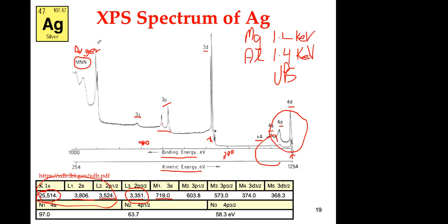The kinetic energy of the Auger is constant, so the Auger peaks are not going to change. In this case, if you plot versus kinetic energy, the XPS peaks are going to change, because the kinetic energy is going to be higher if you use aluminum. If you plot against binding energy, the Auger peaks move. If you plot against kinetic energy, the XPS peaks move. That's a very simple way to be sure whether peaks are XPS peaks or Auger peaks.